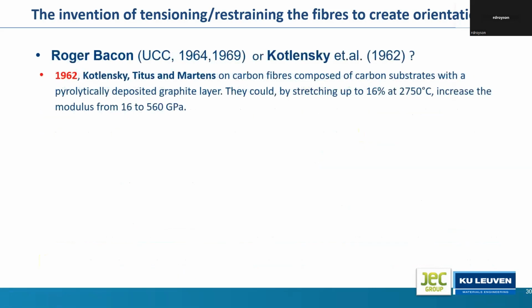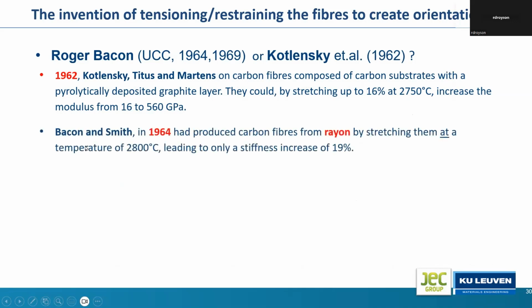And then there is Bacon and Kotlensky. As I said, Kotlensky already in 1962 did some initial research, but they were straining at the carbonization and graphitization temperature. In fact, it was Bacon and his collaborator Smith who in 1964, which is almost exactly the time when Watt, Johnson and Phillips in the UK were doing their experiments on straining, also started stretching at the temperature of 2,800 degrees. That was not very effective.